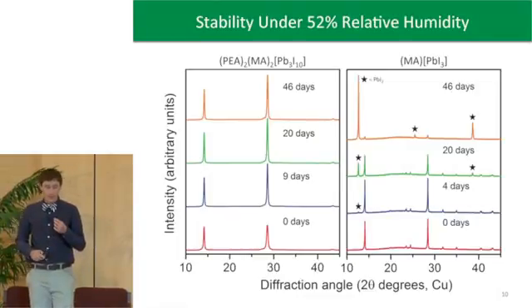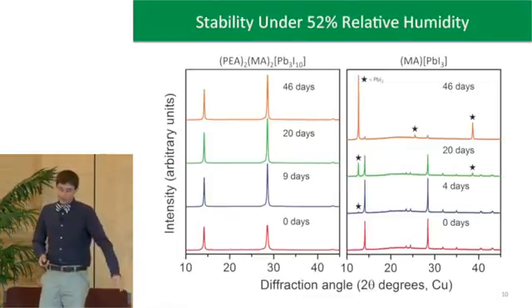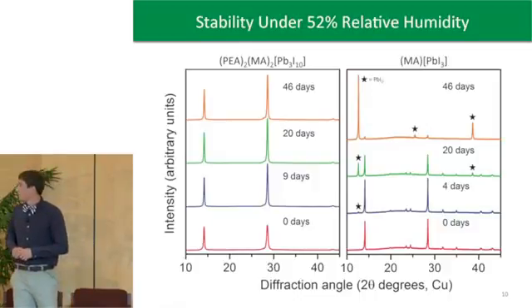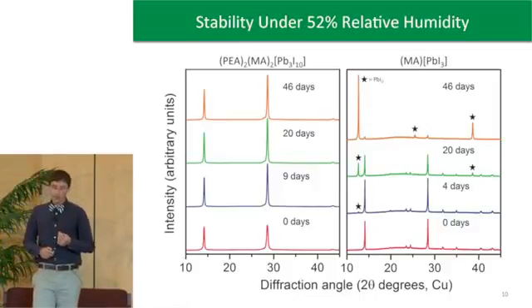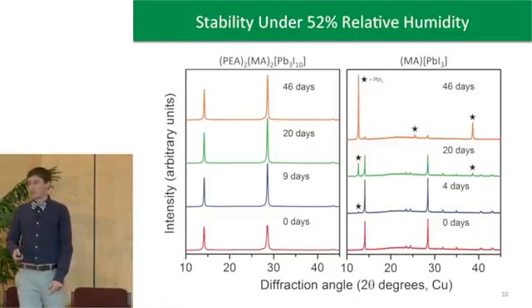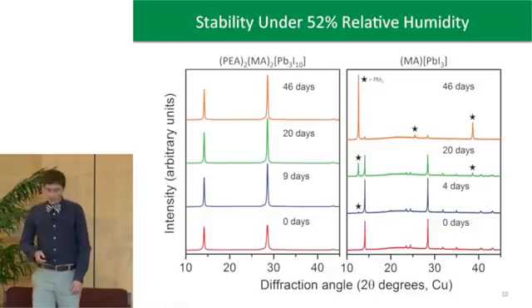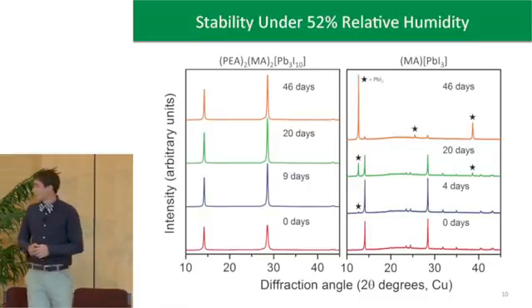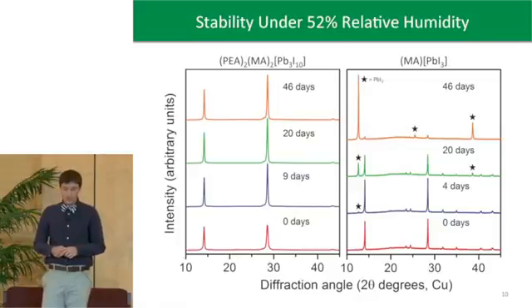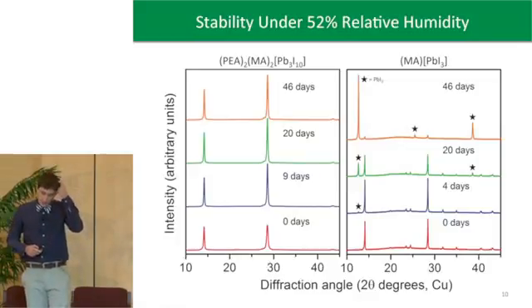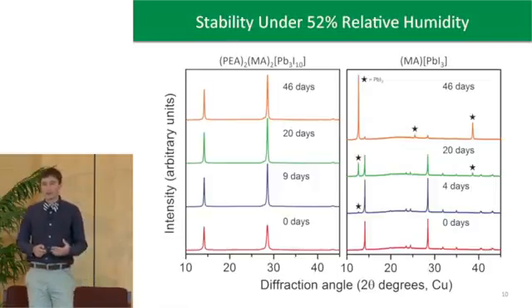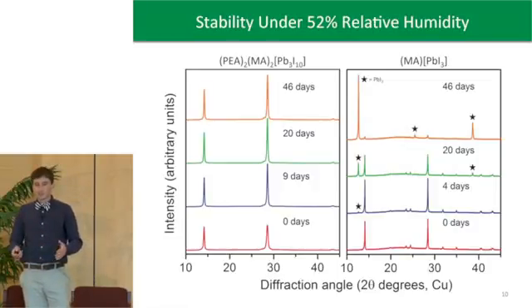Importantly, this material is stable to humidity, both during the deposition and after. Here I've shown a methyl ammonium lead iodide perovskite film that has been exposed to 52% relative humidity over 46 days. Even after 4 days, you see it's starting to convert into PbI2, lead iodide. And after 46 days, it's almost fully converted. However, if you take my material and do the same experiment, after 46 days, it's essentially unchanged.